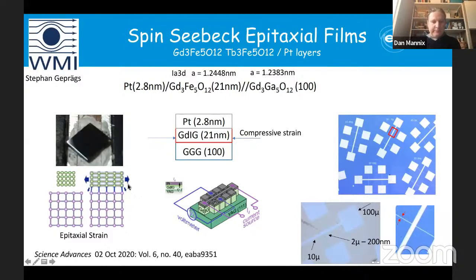What happens to the thin films afterwards is that they become etched by lithography methods into these kind of Hall bar probes here. So this is the Hall bar structure as shown here. The area away from the film is completely etched away. There's only substrate, and all that is left are these Hall bars. This is the part of the sample, and these are crystalline, purely crystalline. So I show a micrograph of the sample over here.